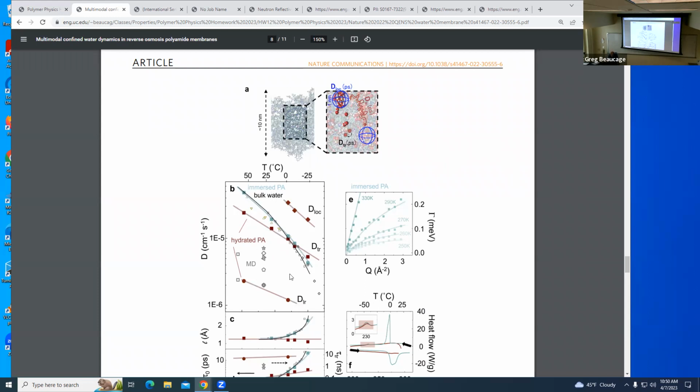So he shows the immersed data. These triangle things, I think, are the previous measurements. So he's got all these things, and the previous people did the same measurement, and they got those triangle things, right? So they're close to the bulk water. Actually, the bulk water is the black. He says their measurements are like bulk water, basically, and that was their conclusion, that the transport through the membrane is bulk water. So there's no separation in it, even though it works. They said it didn't work by this measurement. And he's kind of resolved that it can be picked apart into pieces. All right, so that's that.